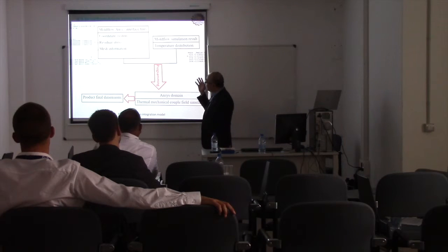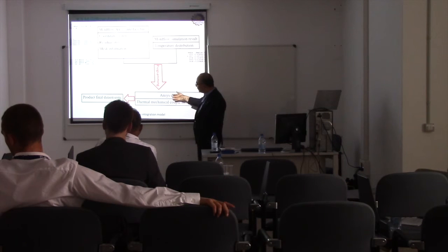Generally, those are the sample data we interpreted from the mold flow result. What you will have from the mold flow is the exact timing. At that time, what is the position of the parts, what is the residual stress, and the mesh information. And then in the mold flow, we also extract data such as temperature distribution. From there, we go to the ANSYS domain, and then we do the thermomechanical coupled field simulation. That is one of the software tools that they have for ANSYS.